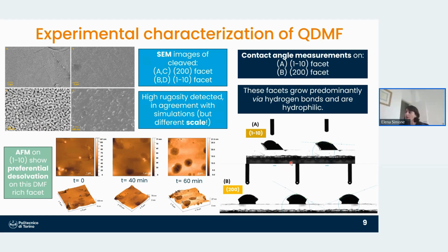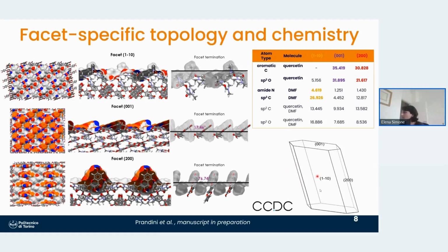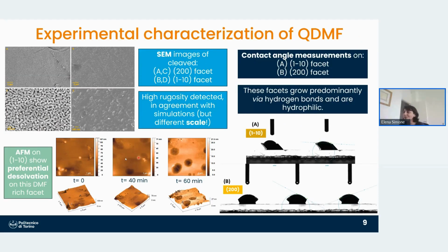And then we tried to do some atomic force microscopy, especially on this large facet over here, which, if you remember, is the one that exposes quite a lot of DMF molecules. And what we saw was very interesting, because over time we start seeing these holes. So those are, again, channels that are formed through desolvation. This was not very expected, because it ruined a little bit our AFM measurements, but it was in nice agreement with the simulation that shows that we have preferential desolvation on this DMF facet.